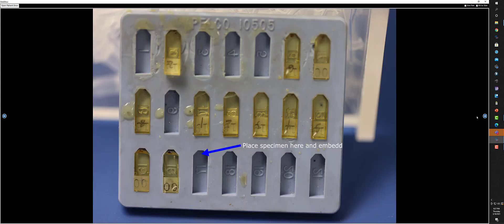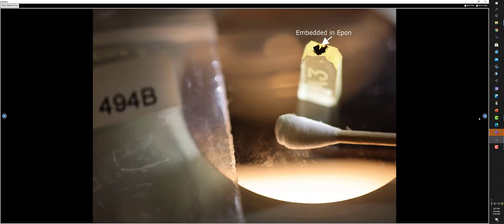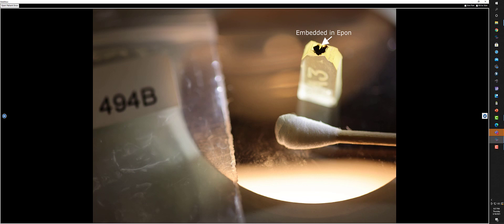When the processing is finished, you place the specimen in one of these forms up near the top, and then you fill these forms with epoxy resin. When it sets, it has to cure for 24 hours in a special temperature-controlled oven. And then when it cures, you get a specimen that looks something like this with the fixed specimen in the top part of the epon.